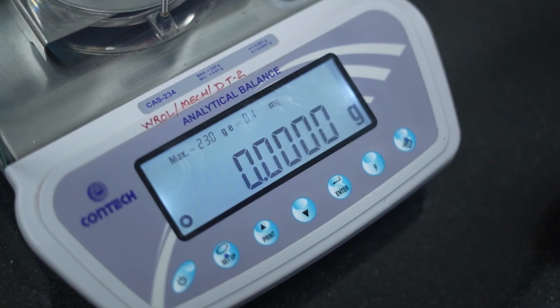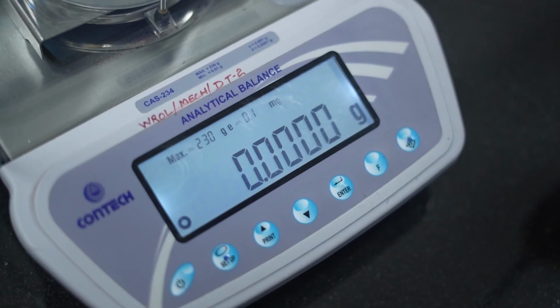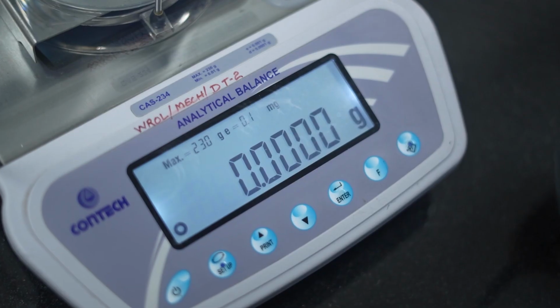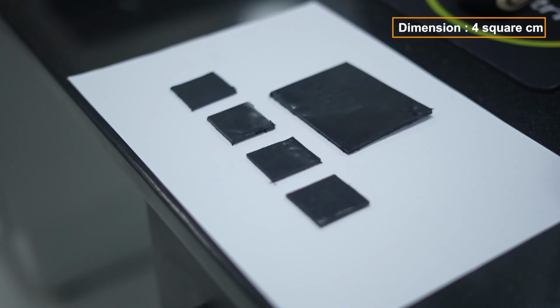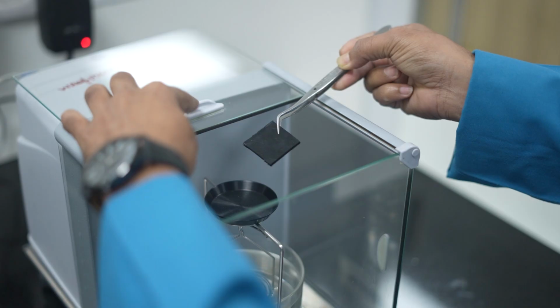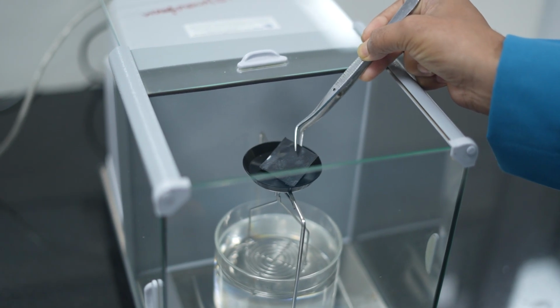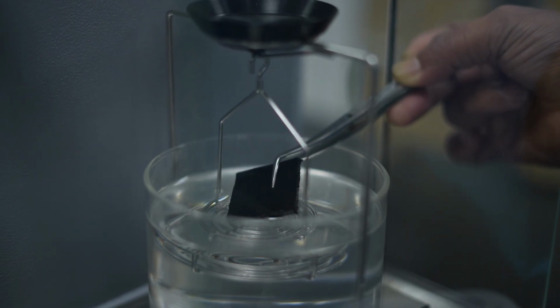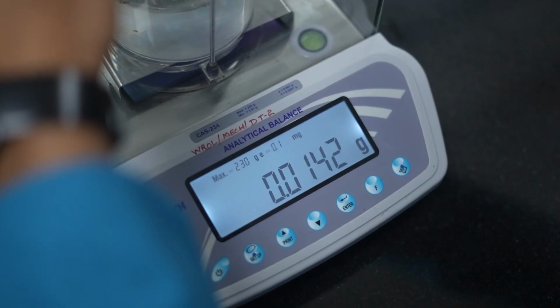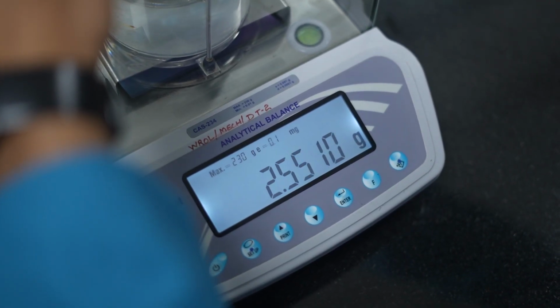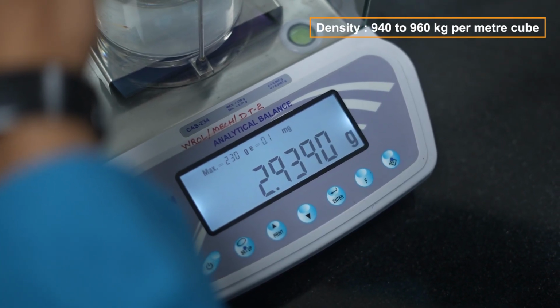Density testing of HDPE pipes as per IS 4984 ensures material consistency, identifies contamination or improper polymer composition, verifies mechanical properties, and ensures long-term durability and performance. The test apparatus includes an analytical balance capable of measuring to 0.1 mg precision. A test specimen of 4 cm square piece is cut out. The specimen is first weighed in air, then submerged in butyl acetate at 27 ± 2 degrees Celsius and weighed again. The density must be between 940 and 960 kg per cubic meter.